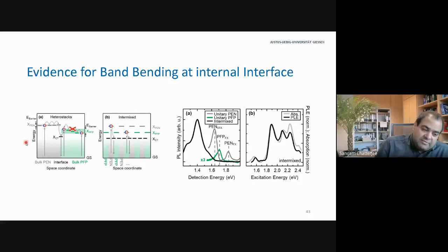You can add three molecules, you can add four molecules, you can add five molecules, and then your computer starts to explode. But if you have five molecules on the left side and five molecules on the right-hand side, you actually start to notice that the pentacene molecules couple very weakly. There might be a little gradient uphill or a little gradient downhill, depending on the functionals you use. So in principle, this is a flat band situation on the one side, where charge transport becomes diffusive, and there are no internal potential gradients to foster this.